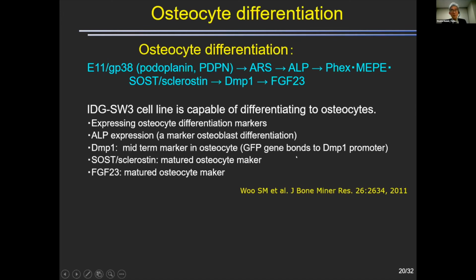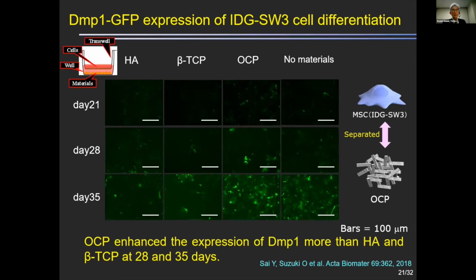And DMP1 can bind to the promoter region of a GFP gene bound to the DMP1 promoter, so we can investigate the differentiation of IDG-SW3 in the presence of the materials. And this is an example of the investigation of the effect of OCP on the osteocyte differentiation in comparison with HA and beta TCP. And we have used a trans-well cell culture, so this means that we can investigate the effect of OCP in the no contact environment of the material.